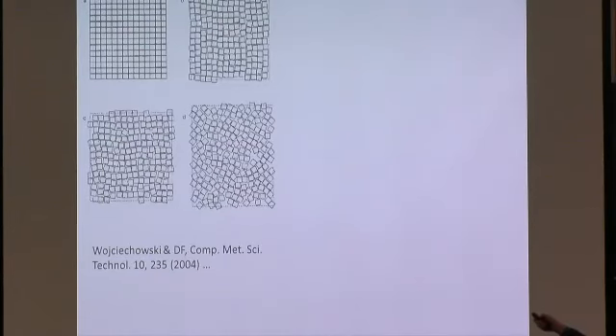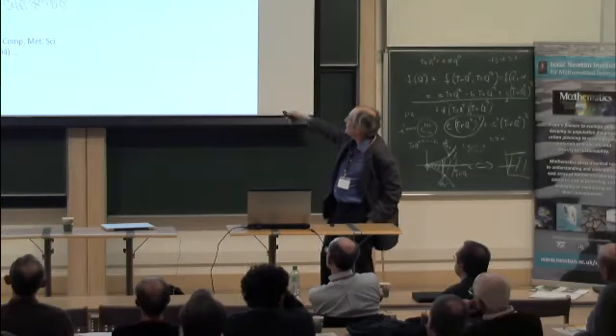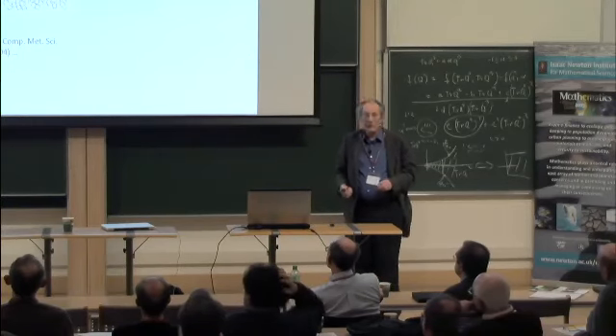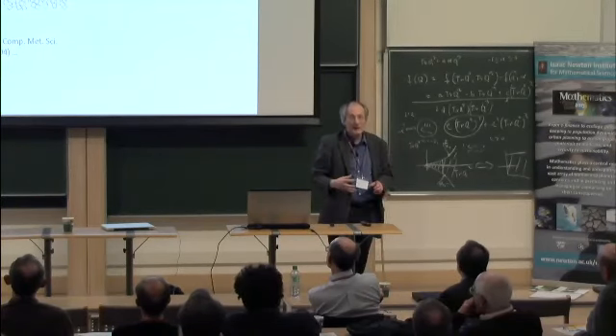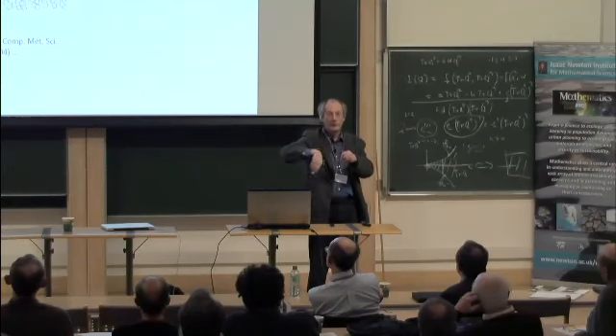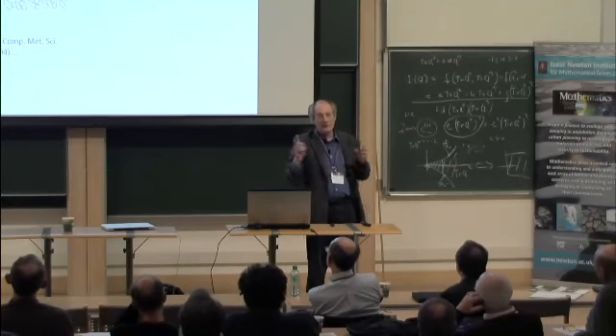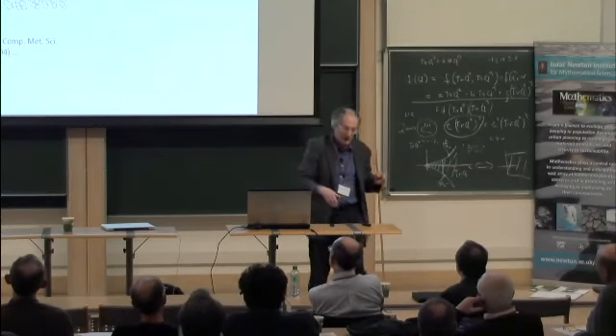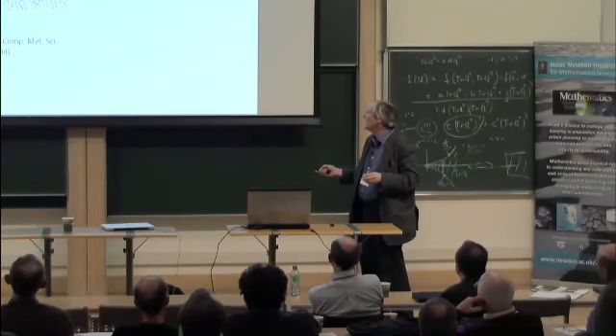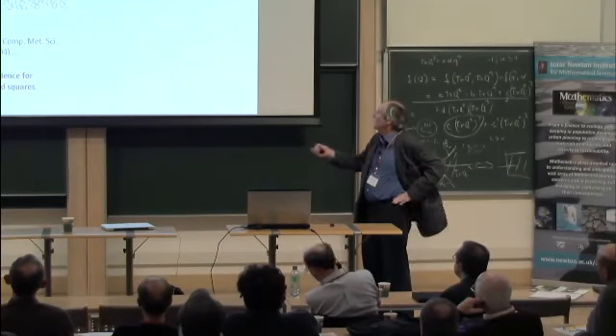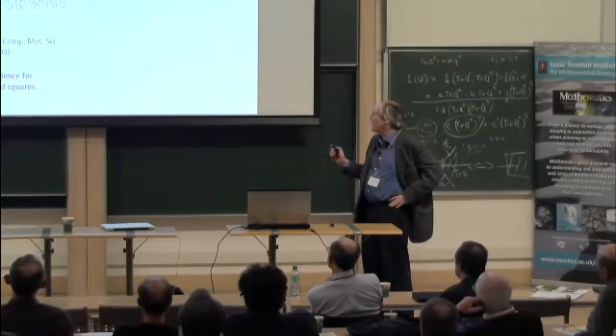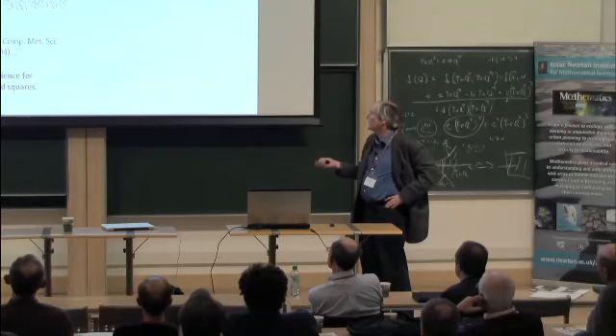As you expand it, you see something that still looks very much like a two-dimensional crystal, and then the lower the density, the more disordered it becomes. And here you see it clearly looks already quite disordered. We were looking for the equivalent of the hexatic phase, where you have six-fold bond orientational order, but in this case we would expect to see a tetratic phase. Now, in these simulations we found evidence for a tetratic phase of hard squares, but